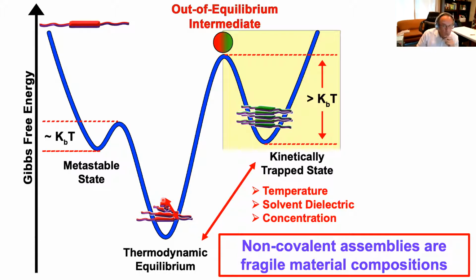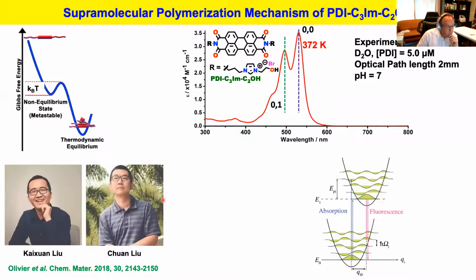And so just to give you an example, the type of building blocks that my lab is working on are these pi-conjugated building blocks. Again, these are rockstars in terms of redox active chromophores, perylene diimide. I'm sure that most of you have heard about it. And the way that we are designing our chromophore, we are flanking them with imidazolium side chains that offer solubility in water. And so under this given set of conditions at high temperature, what we are dealing with is a fully disaggregated sample where these building blocks exist as molecularly dissolved.